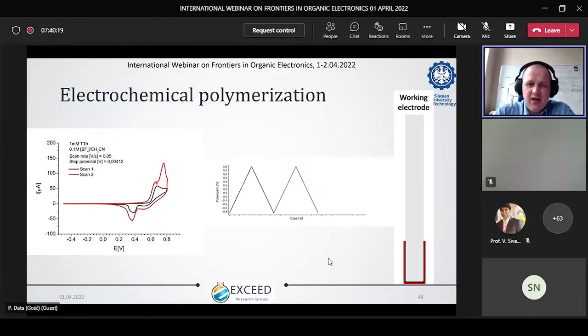With every scan, every cycle, our area is rising, which means the volume of our polymer increases. So in every cycle, we have more and more electroactive species on our electrode. If we formed something degraded here, inactive from the electrical point of view, our current would drop and we would see more of a flat line rather than this very nice reversible increase. And with every step, every cycle, we are growing more and more of our polymer on the electrode.